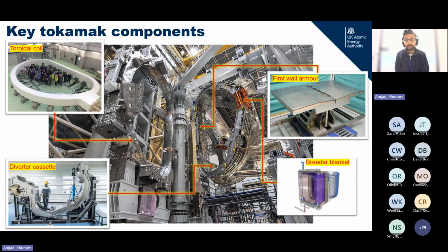So its role is to first of all shield the whole mechanism which could generate the tritium. So it will have the armor, and then it has lithium in it. The design is not yet finalized. There are multiple designs that are being considered, but essentially lithium, when it interacts with high energy neutrons, generates tritium, and then we need a mechanism to retain this tritium and then extract it and then feed it back into the fuel cycle to make the whole fusion process sustainable.